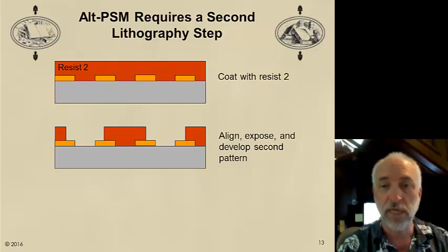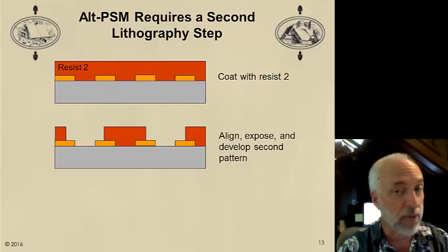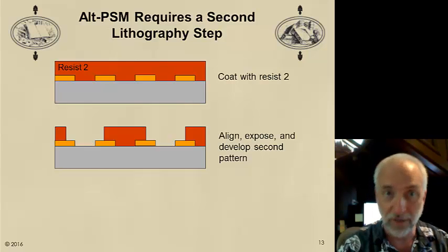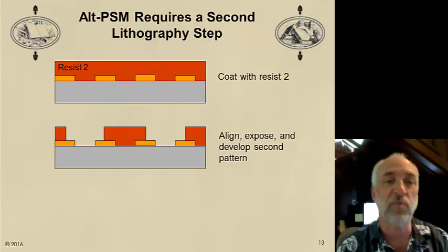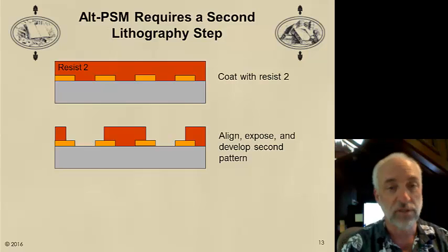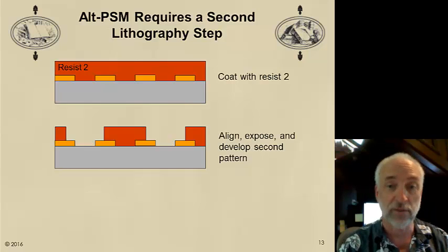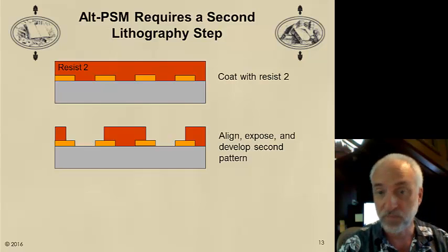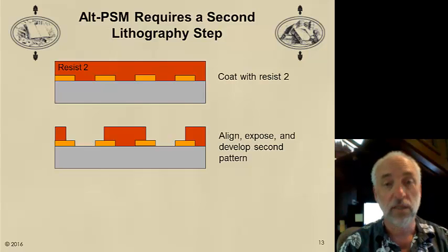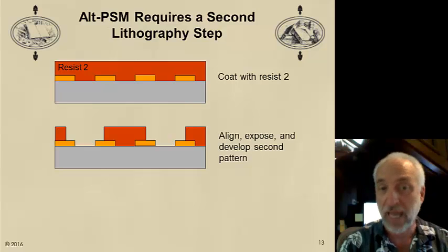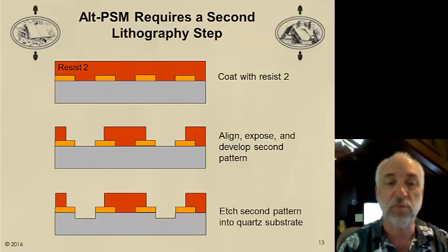Then we do an exposure and develop for a second pattern. But this requires another step, which is new to the alternating phase shifting mask process. The second exposure to the second set of patterns must be aligned to the previous set of patterns. And that's something that's a little bit new. We then use the resist and the absorber pattern itself as an etch mask to etch the pattern into the quartz.